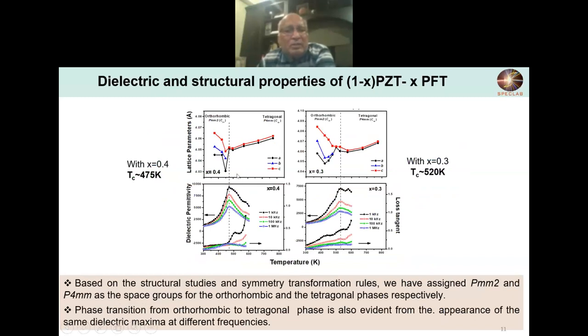We analyzed the same data at high temperature, in a high temperature X-ray. As the temperature changed, we studied how the lattice constants change. You can see here there are three lattice constants, which is orthorhombic. At a certain temperature, only two lattice constants are left, so that is a tetragonal phase. This dotted line clearly tells us where the phase transition occurs.